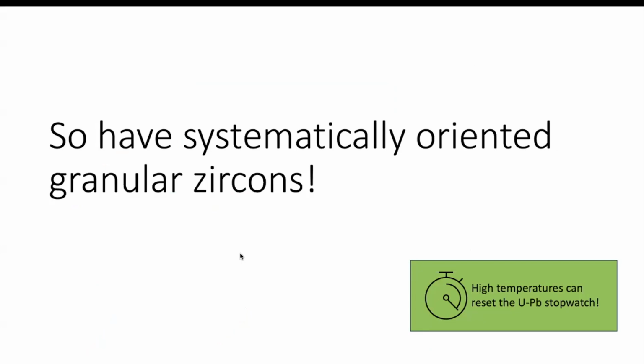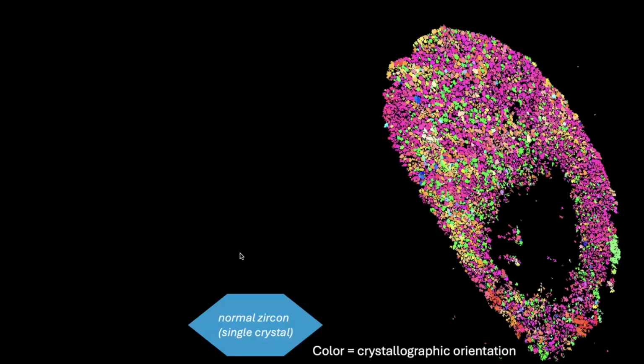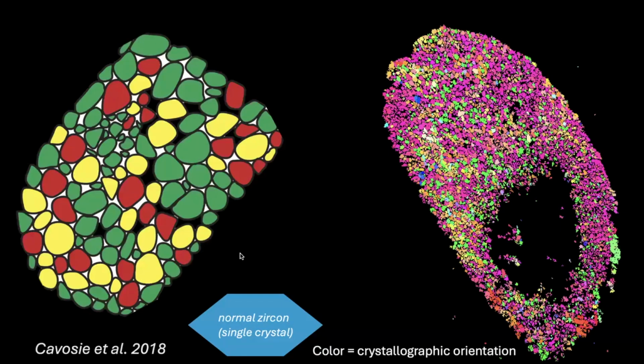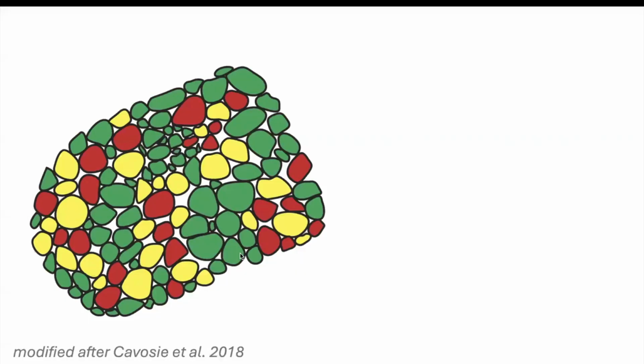To give you a little bit more information about the microstructure, a normal zircon grain is a single crystal with a single crystallographic orientation. We can measure this with electron backscatter diffraction in a scanning electron microscope. Granular zircon is this shock microstructure where the zircon becomes polycrystalline and those different orientations have a 3D geometric relationship. So the one on the right is real data. That's one of my zircons. On the left, it's just a cartoon. This is granular zircon, and I'm going to dive more into those orientations right now.